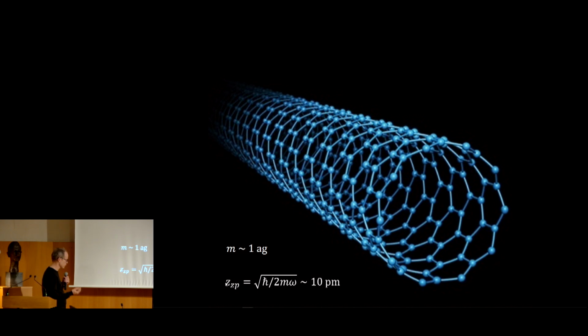And the zero-point motion is very important because when you couple to another degree of freedom, it sets the strength. This is very large compared to what you get with other mechanical resonators. Because the zero-point motion of the nanotube is large, you can couple the nanotube vibration more strongly to other degrees of freedom. This is something important, as you will see in my presentation.